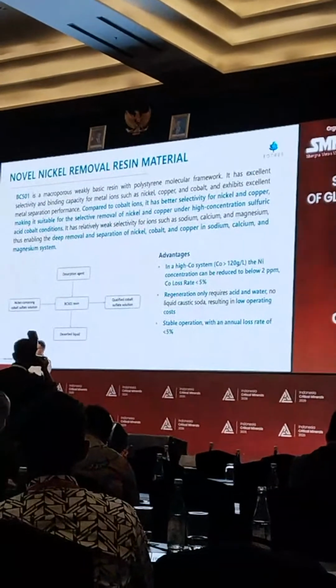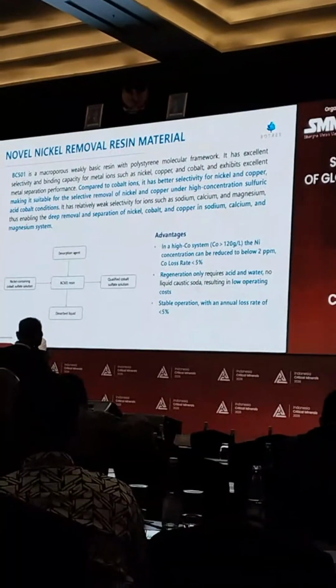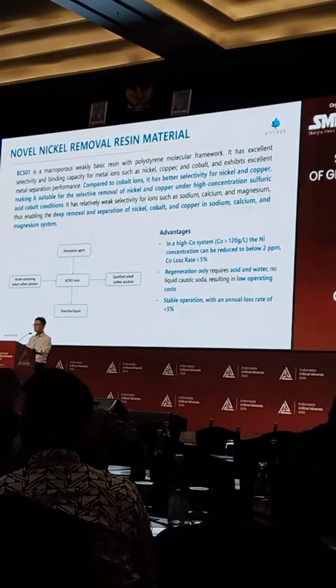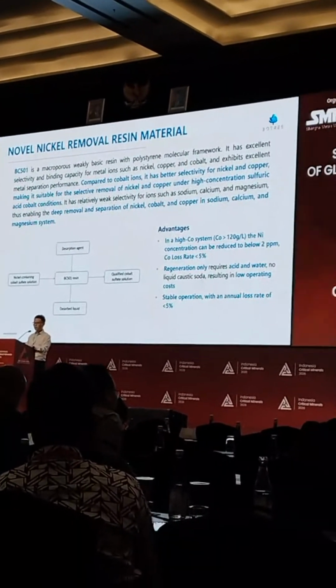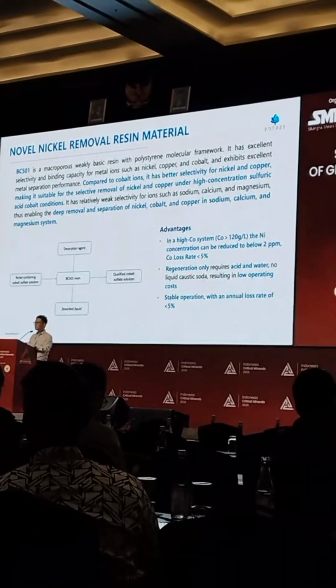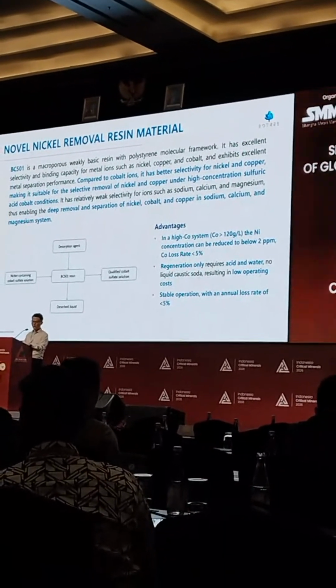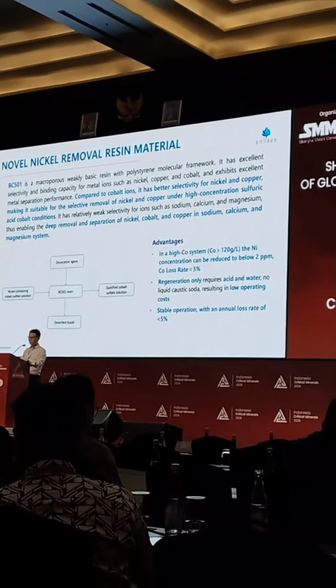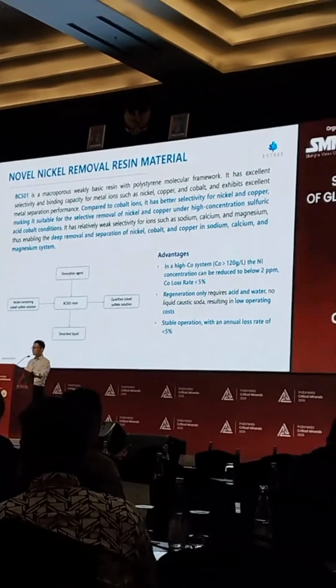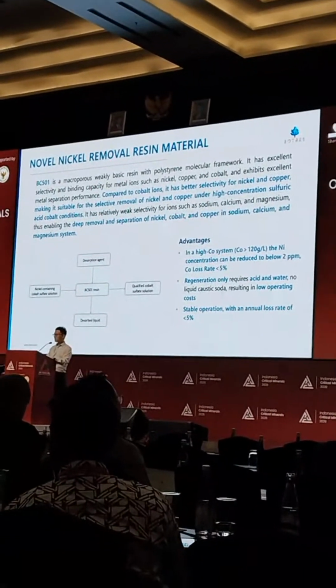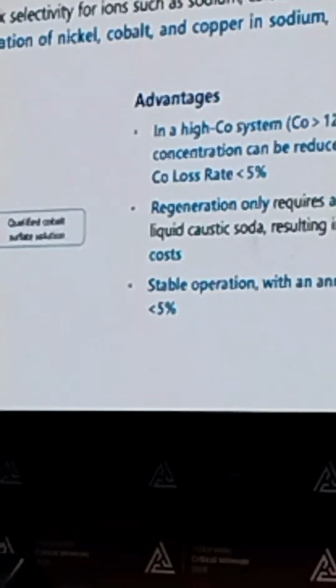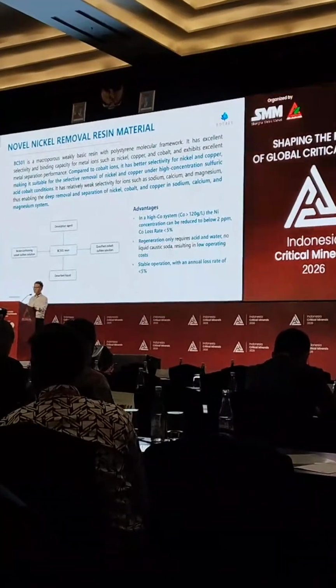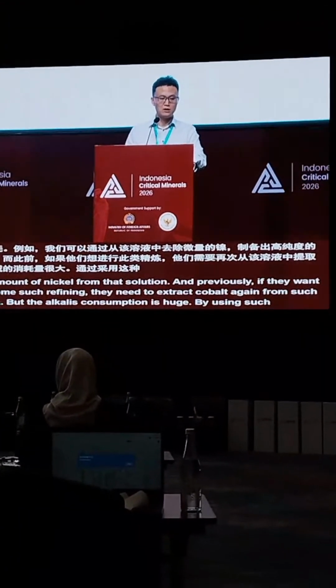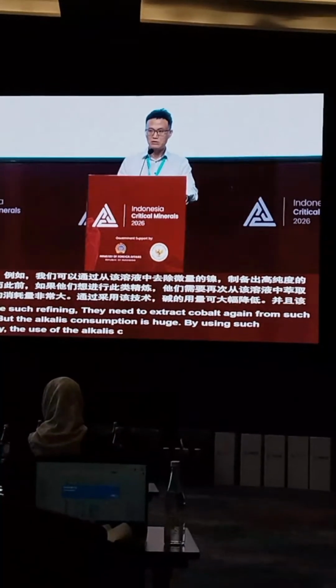Besides the extractants, what we are doing now also includes resins that can also be used for the laterite nickel ore. We can do the adsorption of the nickel using such resins, which can decrease the consumption of alkalis and acids. For instance, we can produce a very high purity cobalt solution by removing a very tiny amount of nickel from that solution. Previously, if they wanted to do such refining, they needed to extract the cobalt again from such solution, but the alkaline consumption is huge. By using such technology, the use of the alkalis can be decreased quite a lot. And for this technology, we are also doing the scale up with some very top manufacturers in this field.